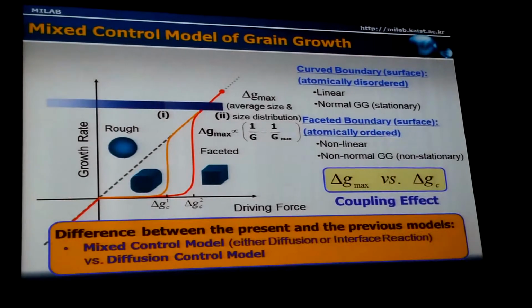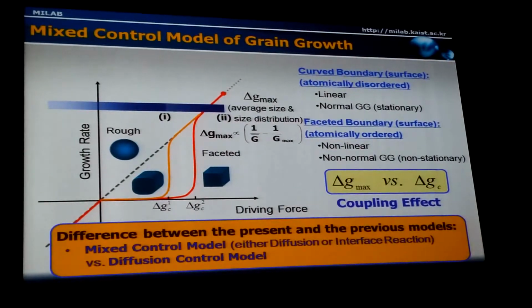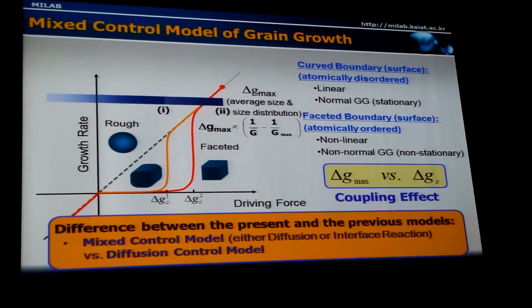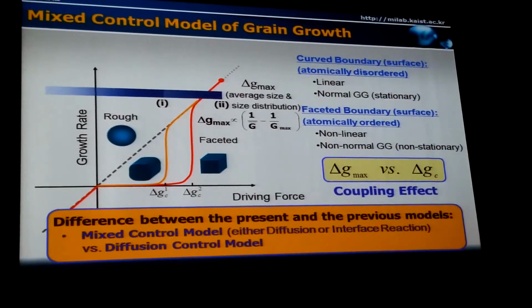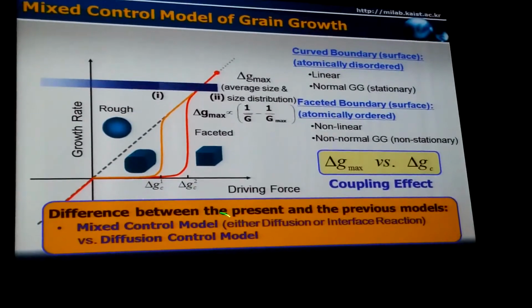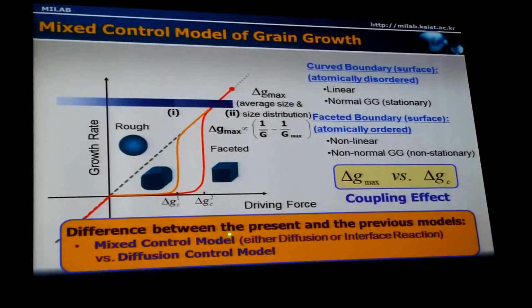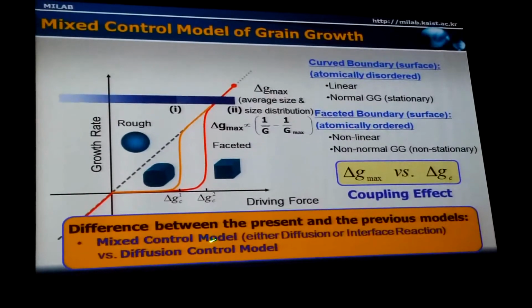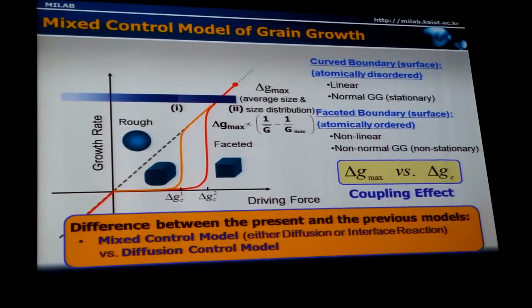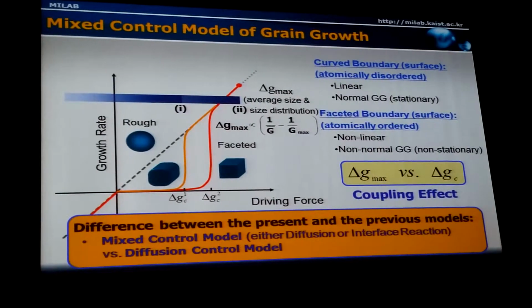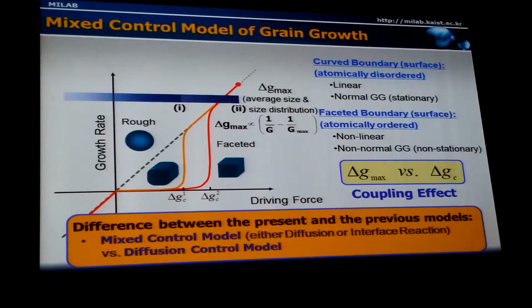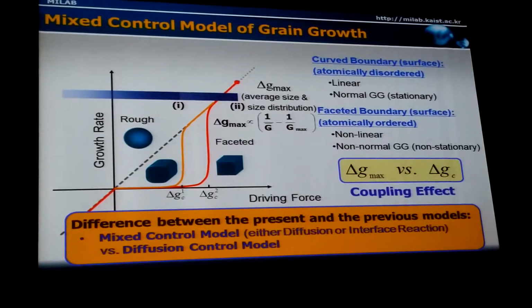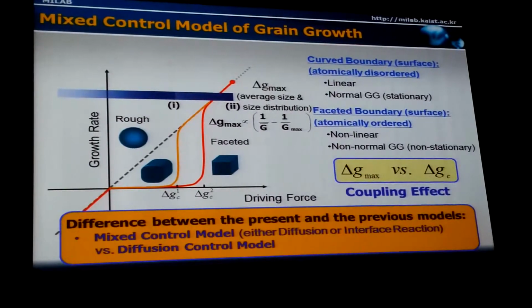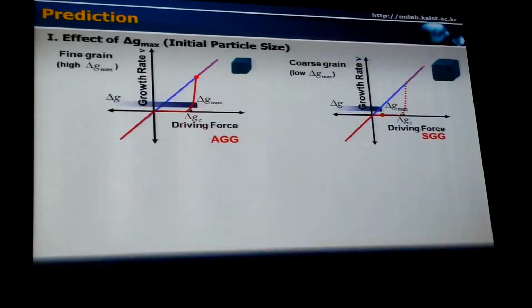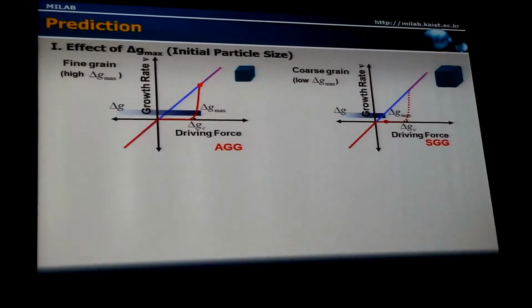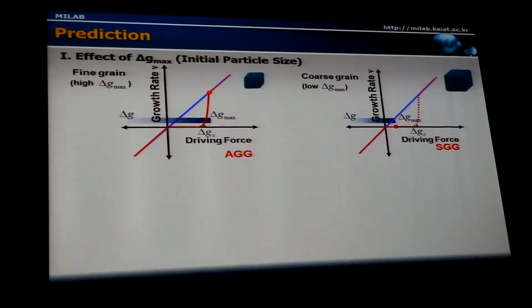This idea, this model, is a totally different model from the classical ones, because in this model, the grain growth is controlled either by diffusion or interface reaction. But in all classical models, the diffusion control was assumed. So there's a fundamental difference between the present and the previous models. This model allows us to predict the effects of various processing parameters on grain growth in polycrystals.